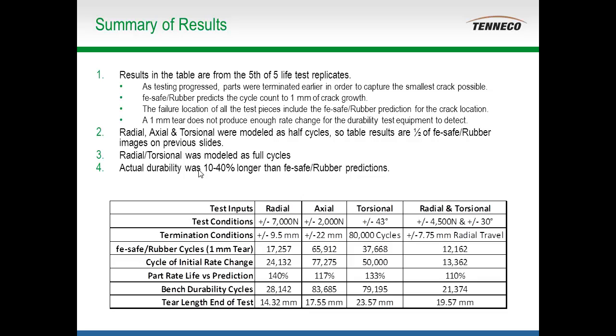But our correlation values, all 4 cases, the actual part lived longer than the prediction, which directionally, to be able to use this as a tool at the quoting stage, that yes, our proposed design will pass a given block cycle, is directionally the way we always want to be. And the parts lived anywhere from 10 to 40% longer than the prediction, depending on the load case. So at least where we are in this stage of our correlation, very favorable results.